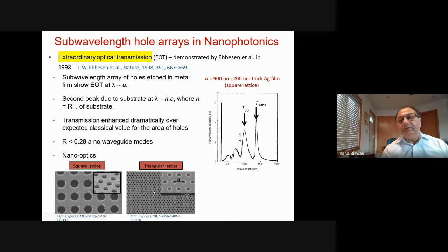And the principal observation is that you have a transmission peak, which occurs at a wavelength very close to the pitch A of the structure. So that's the T00. And in addition, you have a second peak, the substrate peak, which occurs at a wavelength of the refractive index of the substrate times the pitch. So you can see that's quite a sharp, large peak over here.